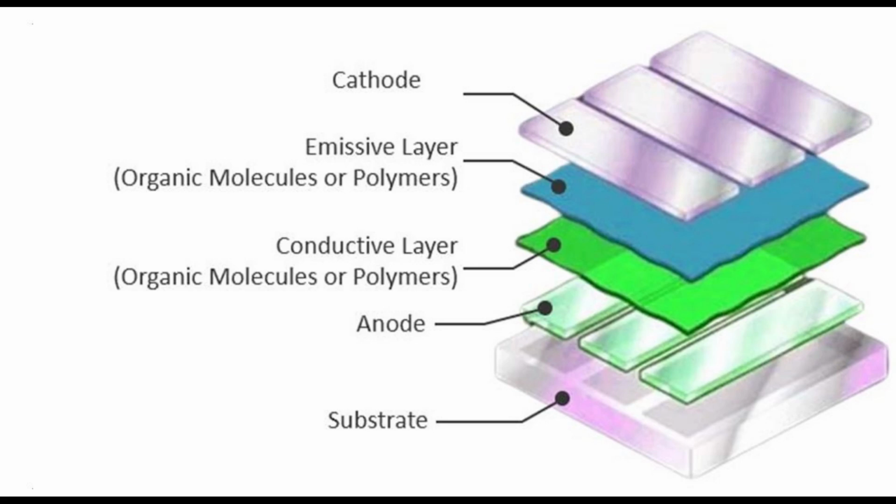a knowledgeable user. More commonly, though, manufacturers optimize the size of the R, G, and B subpixels to reduce the current density through the subpixel in order to equalize lifetime at full luminance. For example, a blue subpixel may be 75% larger than the green subpixel. The red subpixel may be 10% larger than the green.